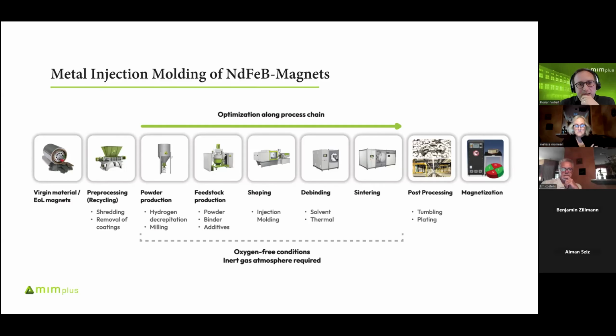Then we have the shaping of the magnet. And now comes the big difference to a polymer-bonded magnet, because the polymer-bonded magnet is done at that point. But for our MIM magnets, we have the next debinding step. That means that we remove nearly 100% of our binder. We do that in two steps, and after the binder is removed, we do the sintering. So then we can sinter the magnet to nearly full density and have our MIM magnet.